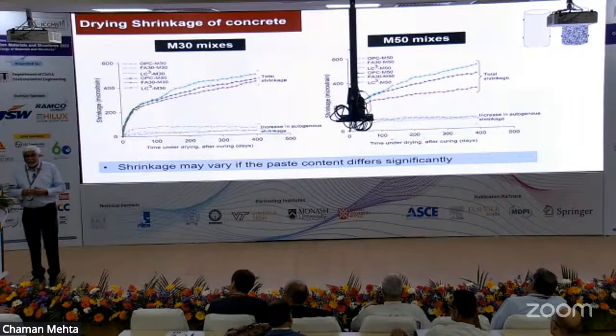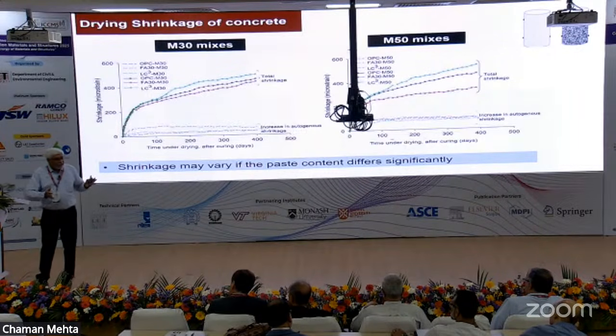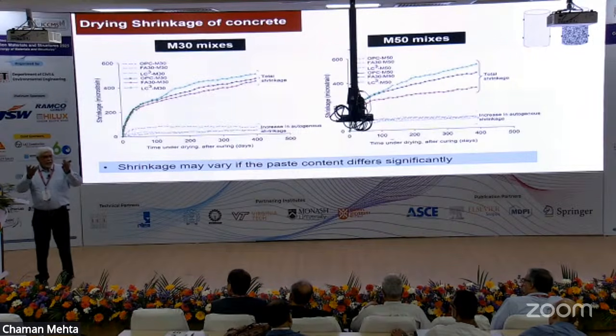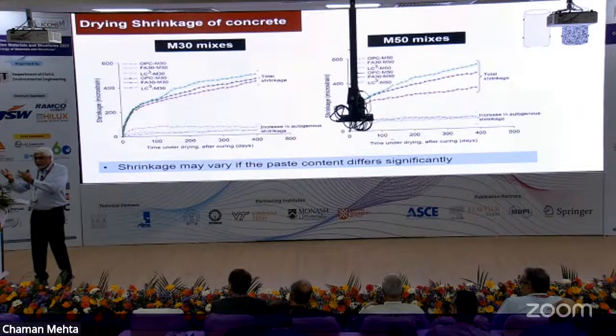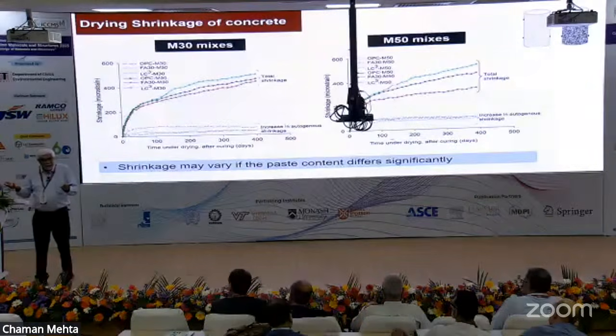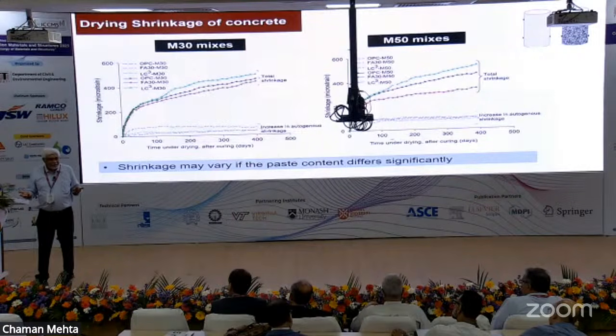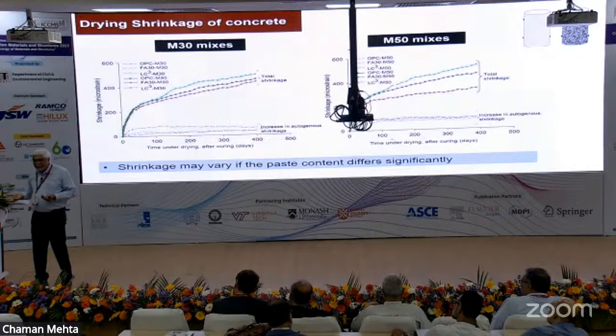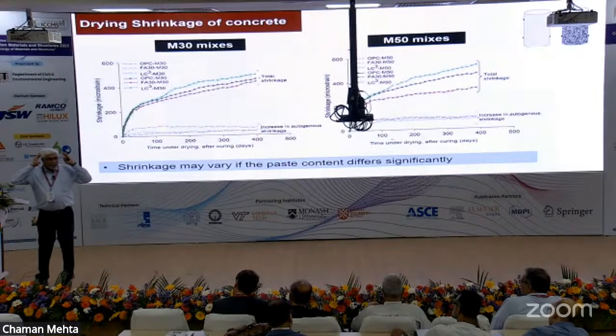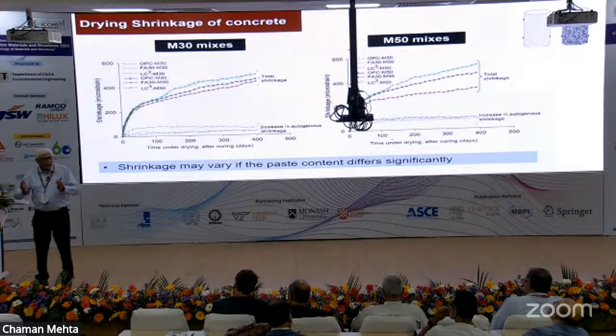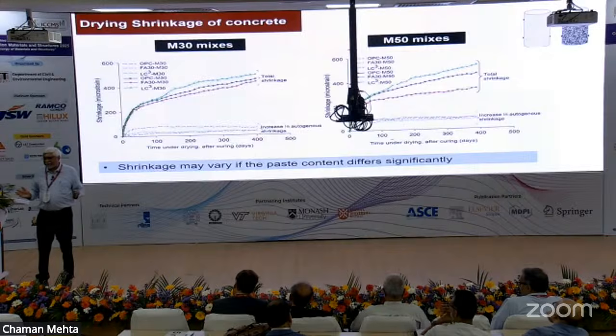Again, about prefabrication, one thing that Professor Prasad and I have seen is when you do prefabrication, you want to remove your element from the mold and take it to site and install. How early? Maybe 3 days. Or your calculations have been done for 28 days. So once the concrete slab is in place, what continues to happen? It continues to shrink. If your joint has been closed, your joint will crack. The joint will open. So these are simple things.